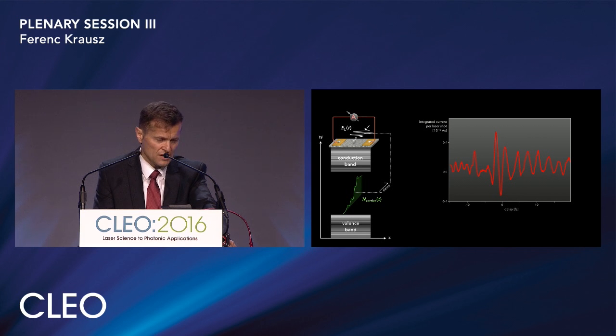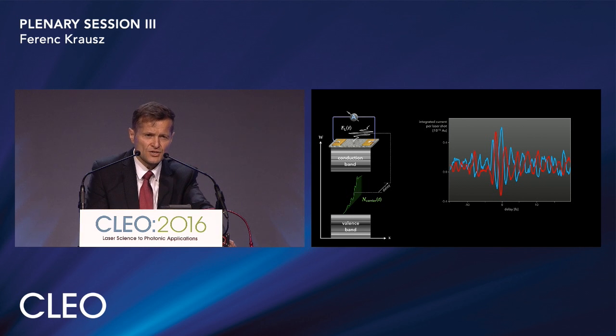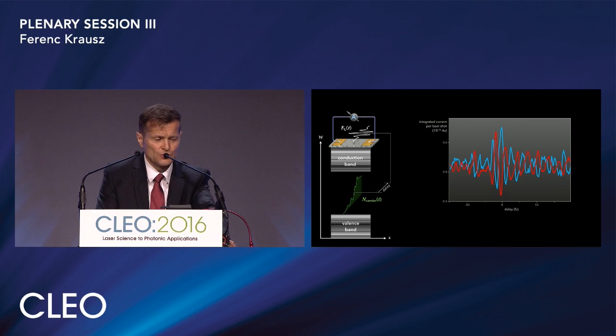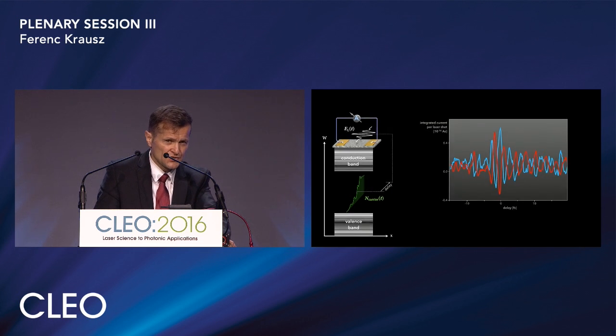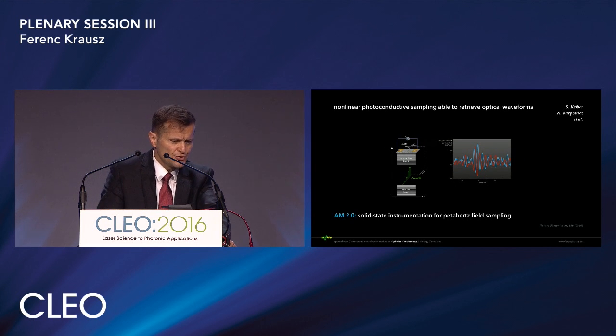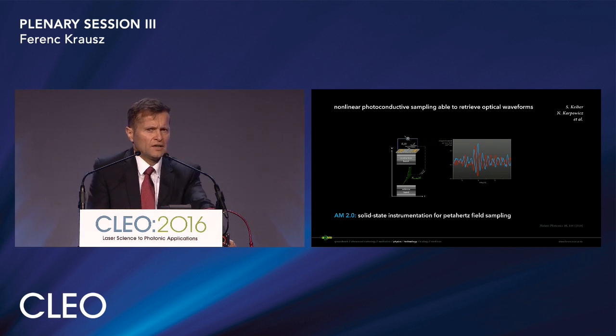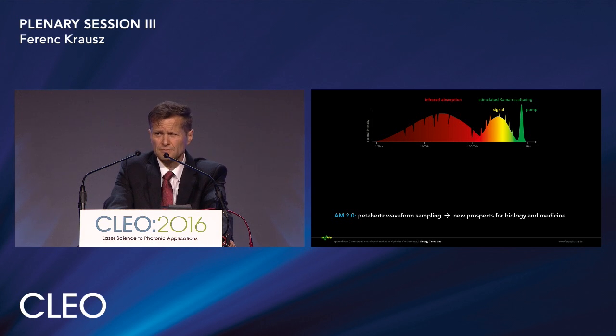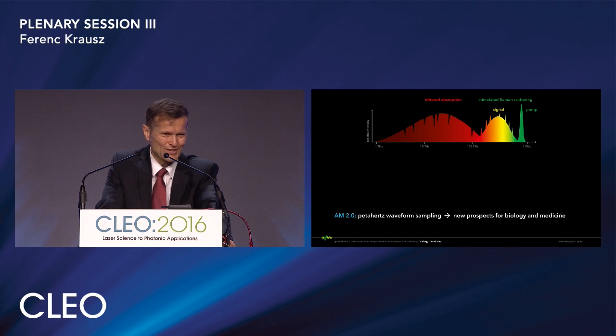This current can be measured as a function of delay between the carrier injection and the optical field to be sampled. Using electro-optic sampling of infrared fields, actually down to a wavelength of about 1.2 micrometer, as a benchmark, Sabine Keiber, Nick Karpowicz, and co-workers have succeeded in testing and also validating nonlinear photoconductive sampling for retrieving optical waveforms up to petahertz frequencies. Petahertz waveform sampling together with few-cycle infrared light will also open, or actually is about to open, new prospects for biology and medicine.